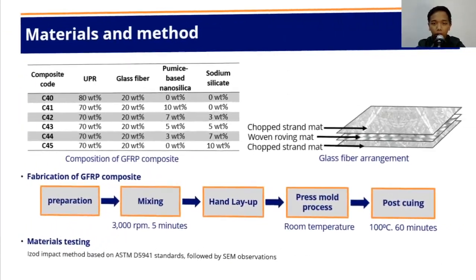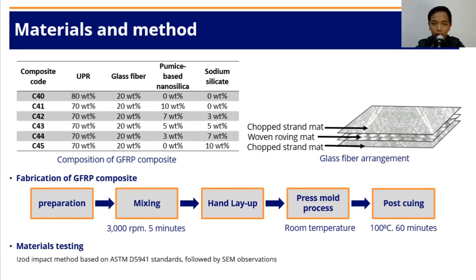And then we are going to the next slide about material and method. In this study, the fabrication of the FRP composite uses a matrix of unsaturated polyester resin mixed with a pumice-based nanosilica filler and sodium silicate according to the concentration listed in the following table. As we can see, the following table displays the content of the GFRP composite.